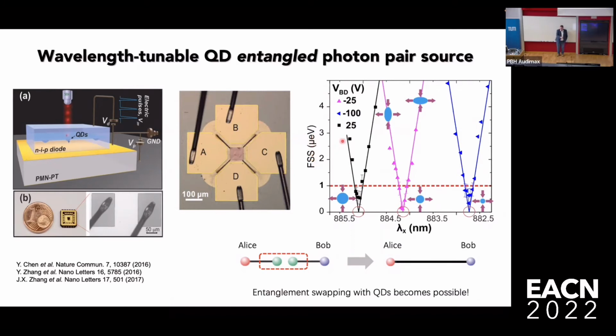excitons. So there you see an example of a quantum dot whereby, by varying essentially a voltage applied to the electro-optical part of the device, they can shift the frequency at which the entangled photon pair source is emitting. And you can also, by using the strain, re-establish symmetry in the system, and therefore reduce the fine structure splitting below the limit of the line width and obtain then good entanglement fidelity. So I think these show very nicely how the device engineering of the semiconductor platform allows you to do this kind of thing.